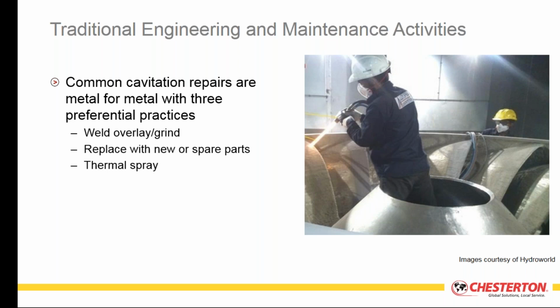When you're using this system, it's very important to have the metal surface preheated so that the surface is properly wet out by that liquefied metal when it impacts on the surface, and it properly cures on the surface. One of the issues with thermal spray-based systems is they tend to be quite porous, so if there is corrosion occurring, the thermal spray system may not be as effective.